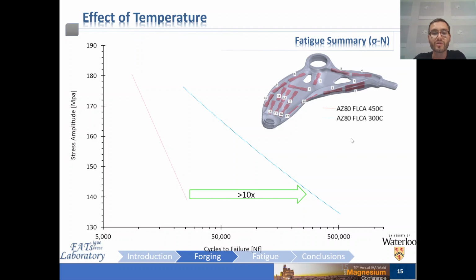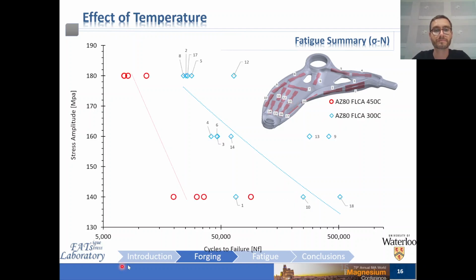So as you can imagine, the physical component is a very complex three-dimensional shape, as you can see in the top right here, and thus the local strain and thermal histories are a function of the location within the component, and they can vary quite a bit. Thus, we looked at characterizing many different locations throughout the component to understand the spatial variation in properties in more depth, and how forging a physical component is fairly difficult in terms of material homogeneity and the properties that you end up with. Now overlaying the individual data points over these SN curves or these idealized curves that you can see here, one can easily appreciate that even at the component level of forging, there's a large amount of variability in the properties, which is highly a function of the location within the forging itself and the thermomechanical history that that specific location experienced.